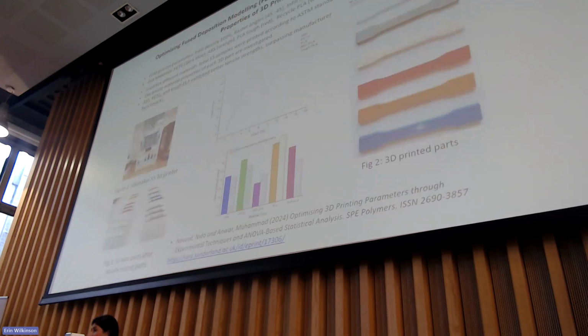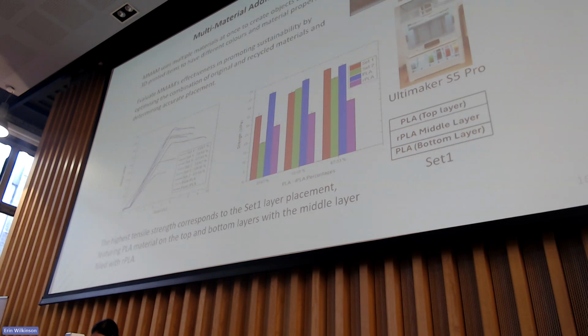And then we applied this research on different materials, and we got very good results. We found out the set of the parameters that we explored is very good, and we can get a very good strength out of it, which is more than the strength that the manufacturer specifies. So yeah, very good result out of it.